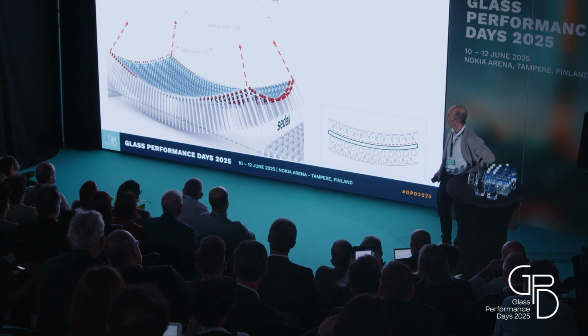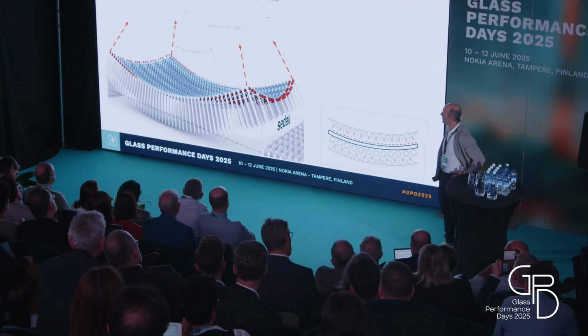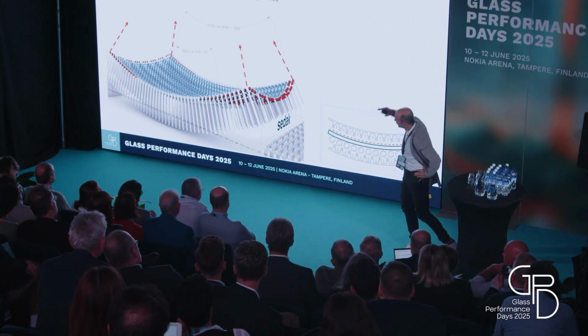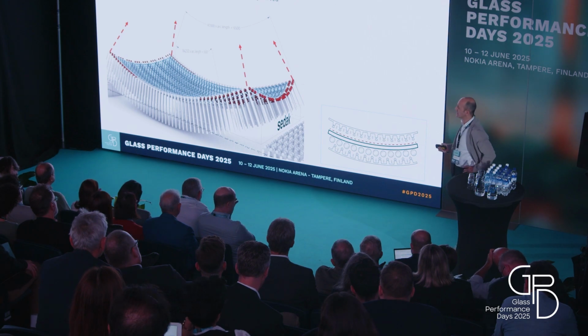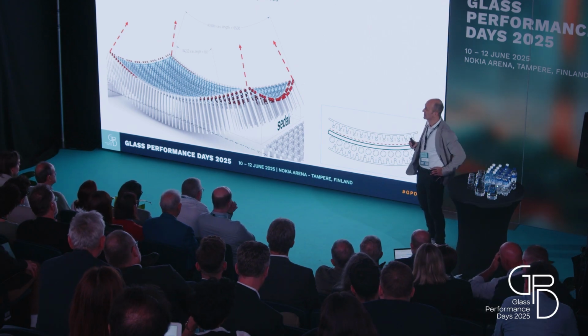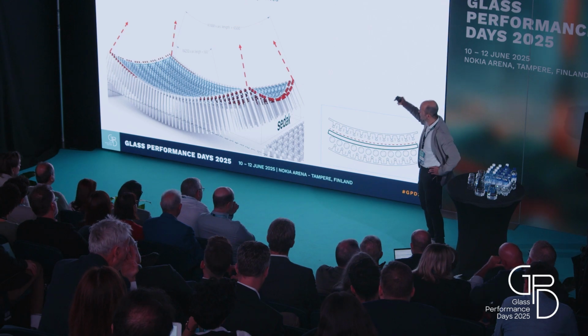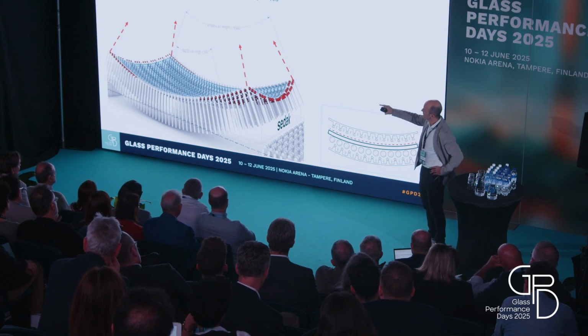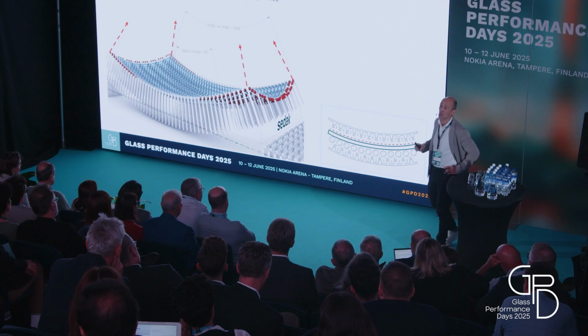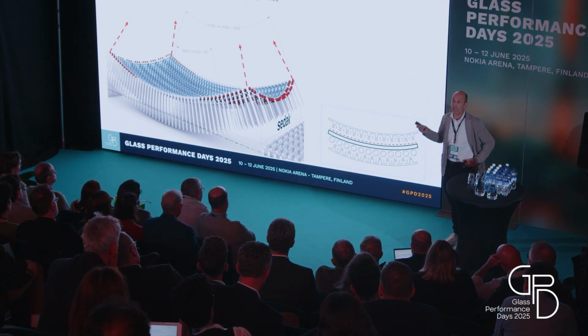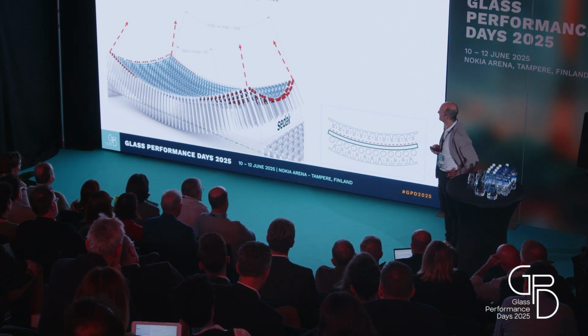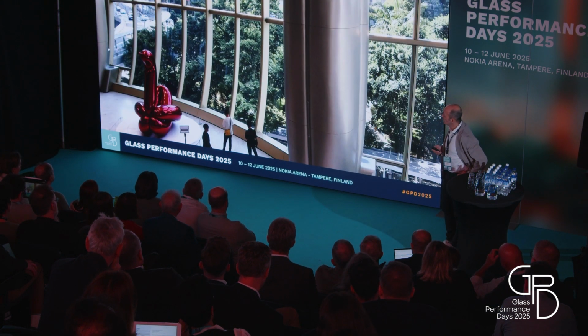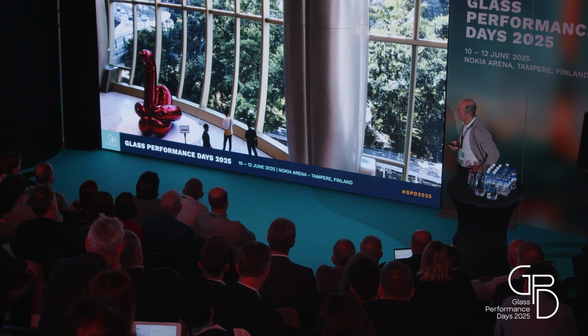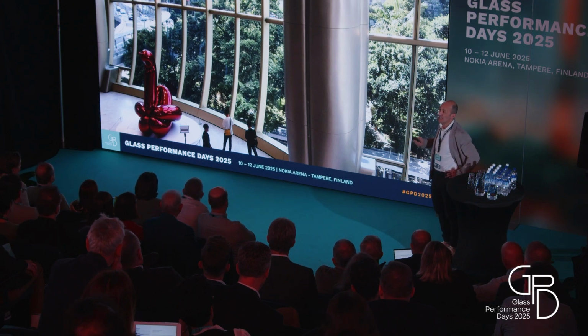So being able to bend in two directions, really. Being able to manufacture and deliver spherical panels. But having an oscillation of the panel in the long direction, so also once again being very limited, and also because the center of this rolling structure is fixed to the main structure, this oven cannot go up and down, just the four corners, so not being able to do any sort of anticlastic geometries. That's a view inside out of the same building. I think it's good to show that because it's the first time glass like this has been produced, spherically, doubly curved, toughened, laminated, and the optical quality is outstanding.